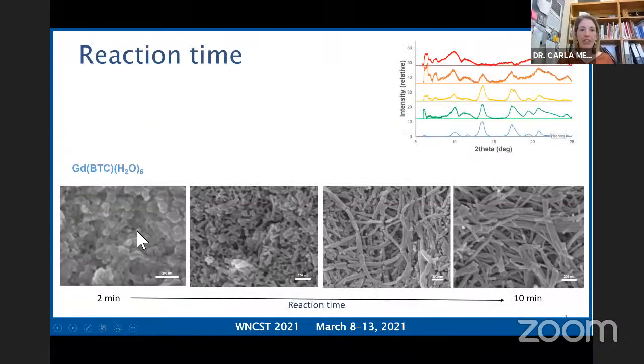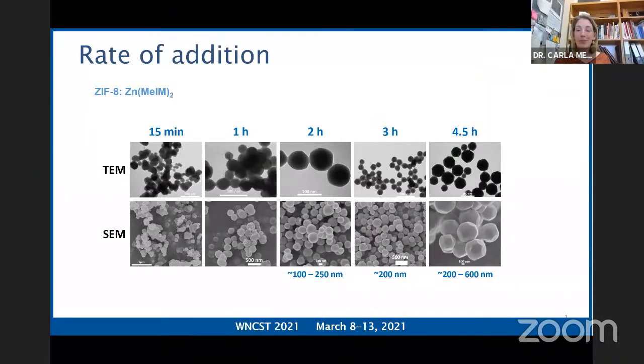And we've quite simply varied the reaction time. So that means we have mixed microemulsion 1 containing the BTC ligand and microemulsion 2 containing gadolinium chloride. We've mixed them together and allowed them to react for 2 minutes, 4 minutes, 6 minutes, and 8 minutes. And as you might expect, you can see the growth of these, what we can call nanorods, perhaps. But interestingly, these form in 10 minutes at room temperature. And if we follow the X-ray powder diffraction pattern, as you might expect, again, we see an increase in the crystallinity the longer we allow these to react.